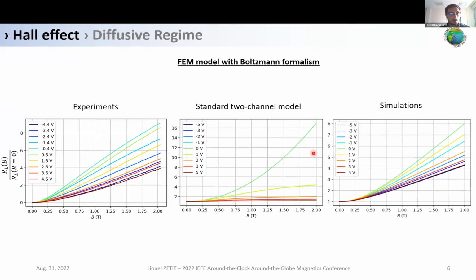From this same model, we developed a more complex one. It's an FEM model that allows every parameter to depend on position. And among the effects that our model can reproduce, I will talk about the linearity of magnetoresistance. Because if you conduct experiments, you can see that at a certain point, the longitudinal resistance is linear versus the magnetic field. And if we simply take the two-channel model that I presented previously, we cannot have this linear behavior.